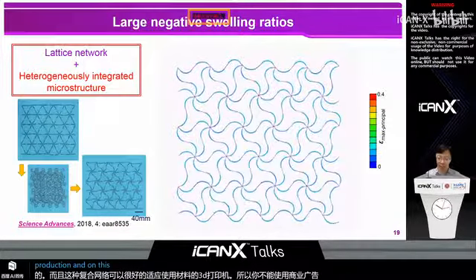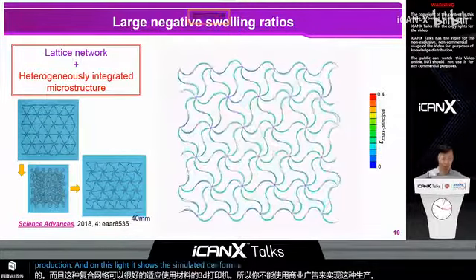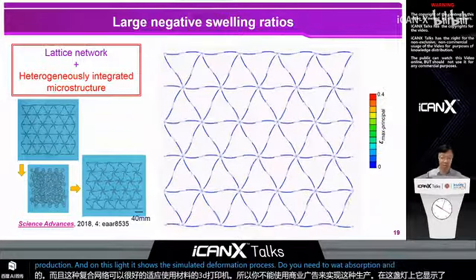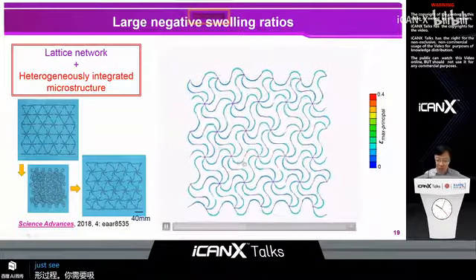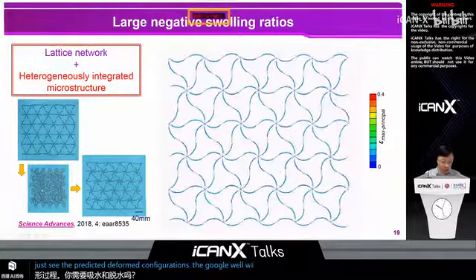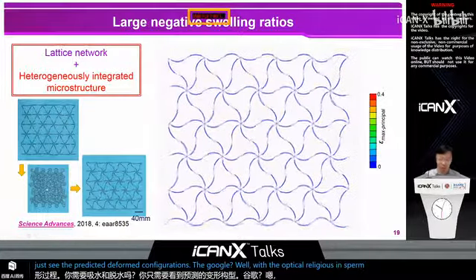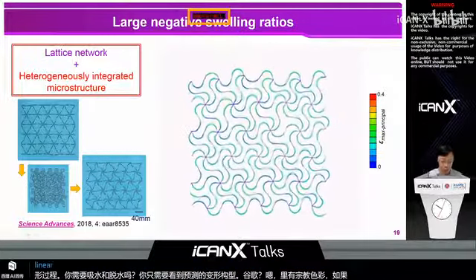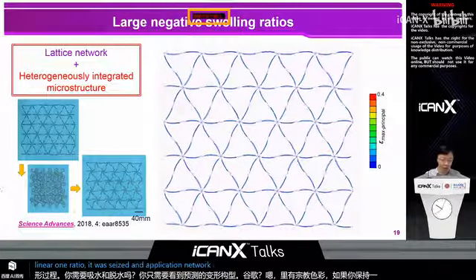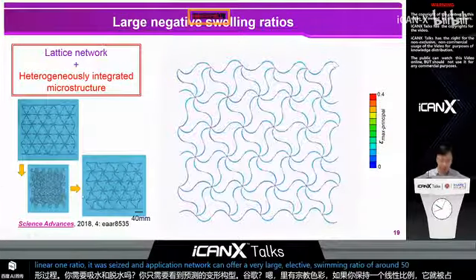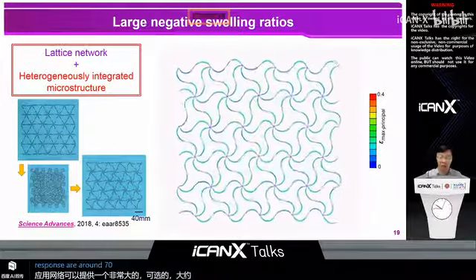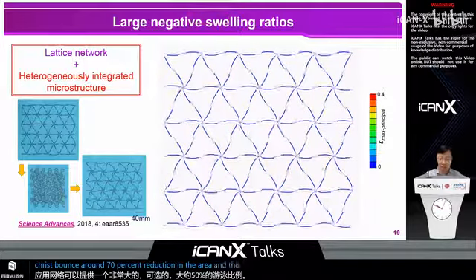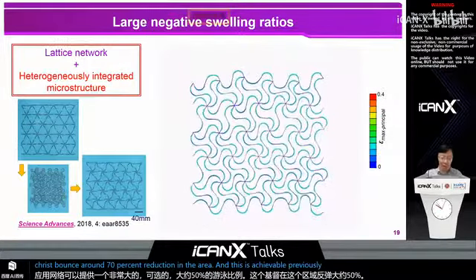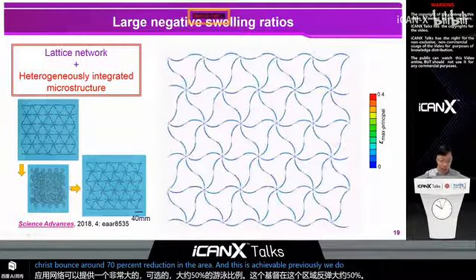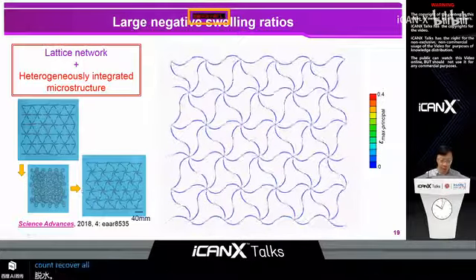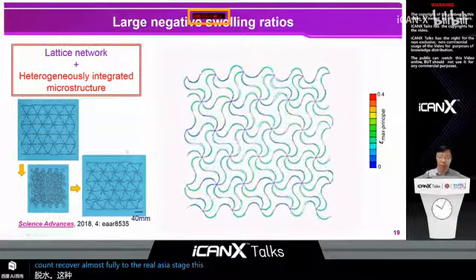On this slide, it shows the simulated deformation process during water absorption and dehydration. You can see the predicted deformed configurations agree very well with the optical images in experiments. If you calculate the value of the linear swelling ratio, you will see that this fabricated network can offer a very large negative swelling ratio of around 50%. This corresponds to around 70% reduction in area, and this was unachievable previously. When you do dehydration, this kind of structure can recover almost fully to the initial state. This indicates good reversibility.